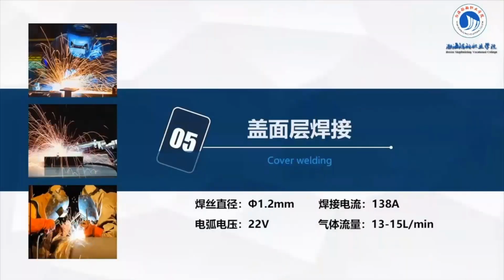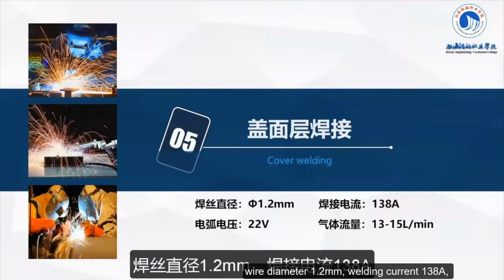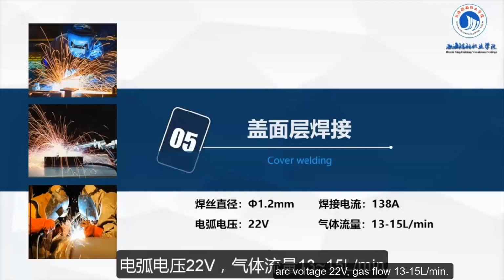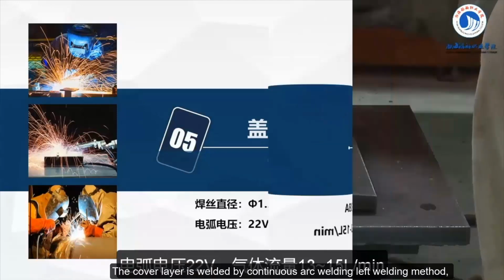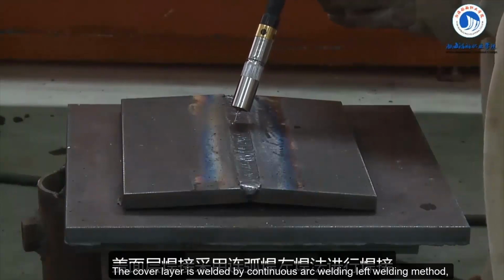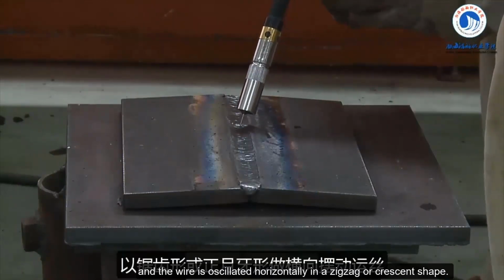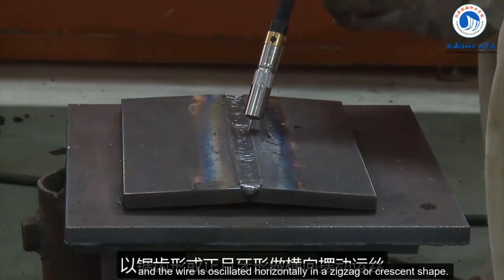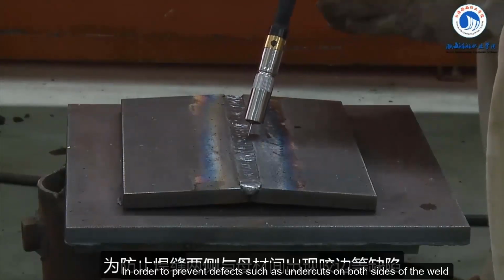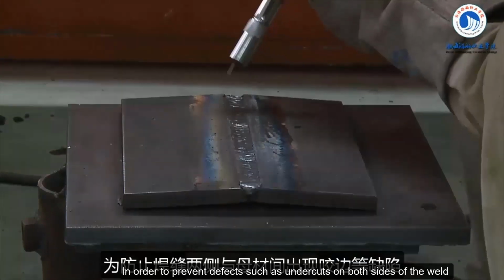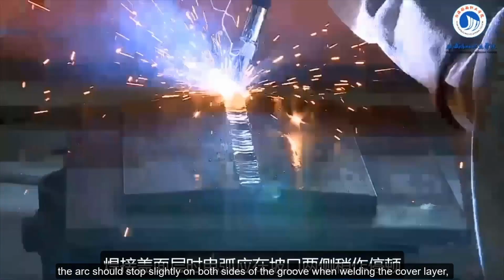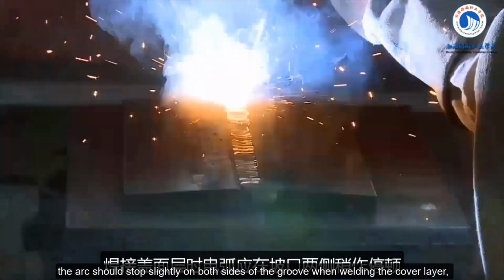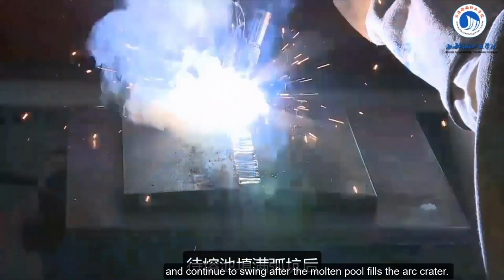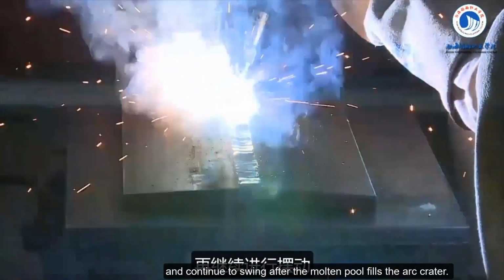Cover welding. Wire diameter 1.2 mm, welding current 138 A, arc voltage 22 volts, gas flow 13 to 15 L per minute. The cover layer is welded by continuous arc welding left welding method, and the wire is oscillated horizontally in a zigzag or crescent shape. In order to prevent defects such as undercuts on both sides of the weld and the base metal, the arc should stop slightly on both sides of the groove when welding the cover layer, and continue to swing after the molten pool fills the arc crater.